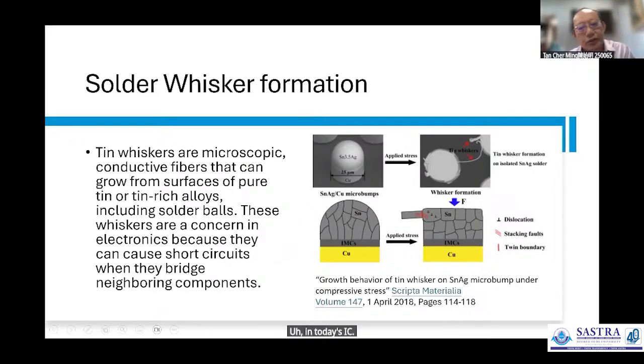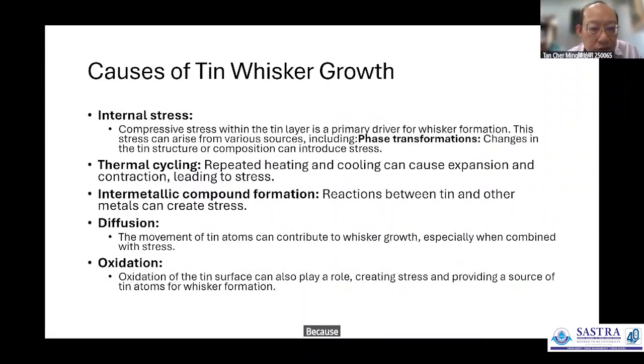Why is it serious in today's IC? Because in the early days, we used a lead solder. When you put lead in the solder, the tin whisker is suppressed. But the moment when people changed to the lead-free solder, tin whisker grew in an amazing way. And so without a good understanding, when people changed the lead solder to the lead-free solder, tin whisker became a very serious reliability issue, even until today.